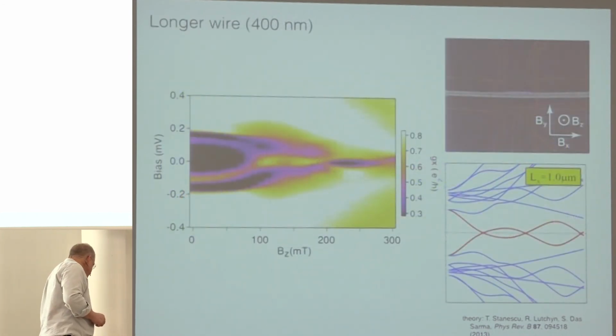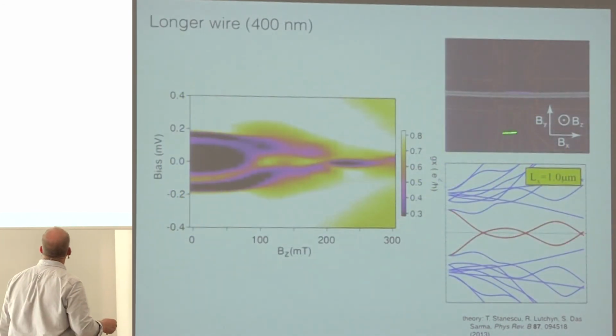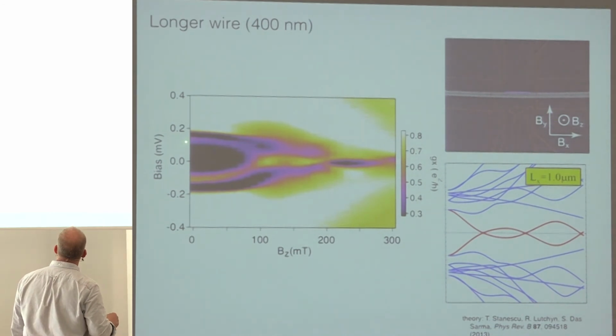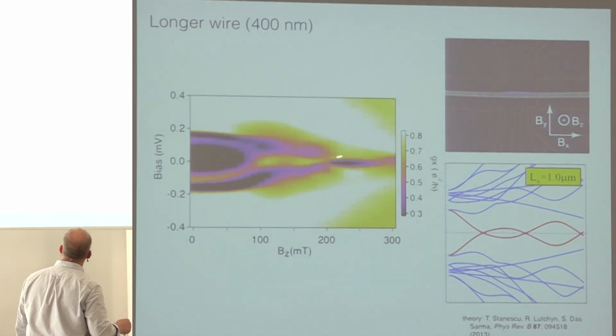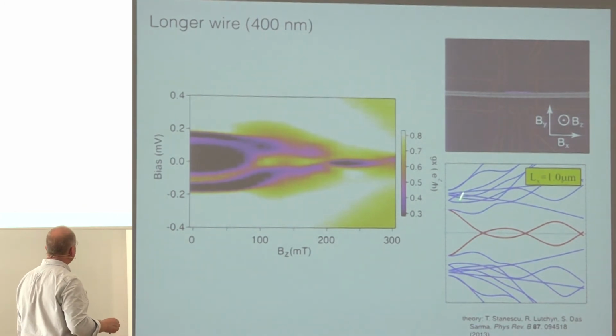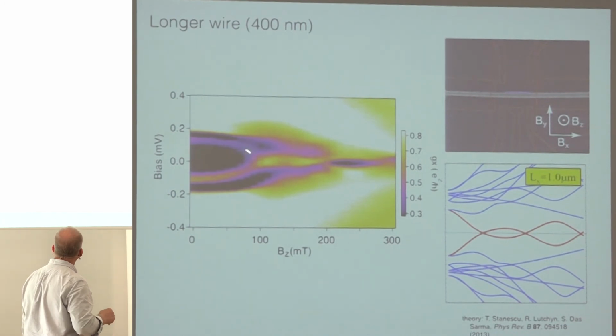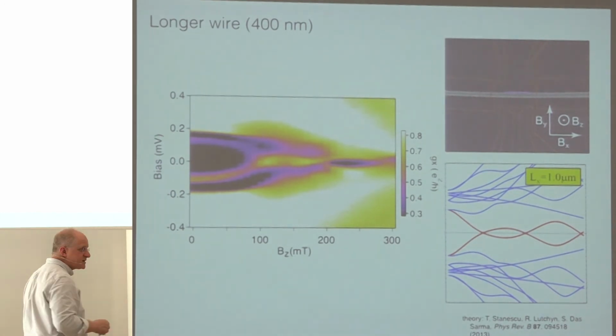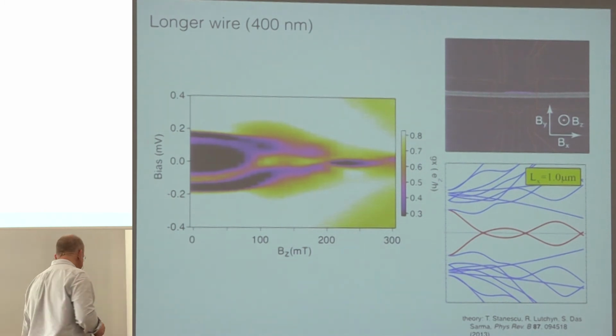By the time we make the device longer, here's one that's twice as long, 400 nanometers, then those states, as you follow them, do pretty much exactly what you might expect those subgap states to do. That is, they're not quite Majorana states because they pass by each other, but they come pretty close and they oscillate just as you would expect them to do.